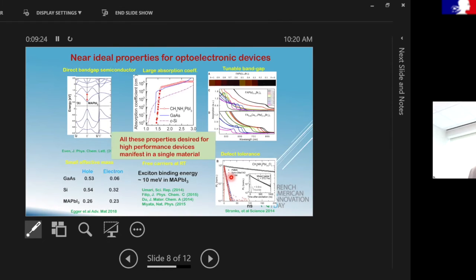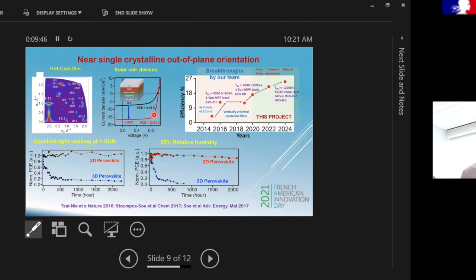Okay. And so another cool thing about this is that all these properties exist in a single material. And that's sort of the magic and the wonder of these halide perovskites. And that's why they've become such an interesting semiconductor material for different things. And so in addition to photovoltaic devices, here's a chart where, as I said, we've been focused on these two-dimensional perovskites since about 2015, because we found, in this 2016 seminal paper, that the 2D perovskites are way more stable than the 3D perovskites.